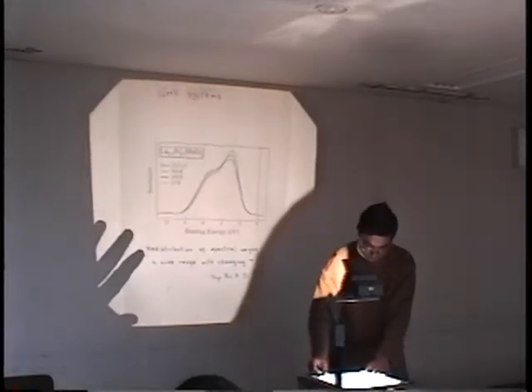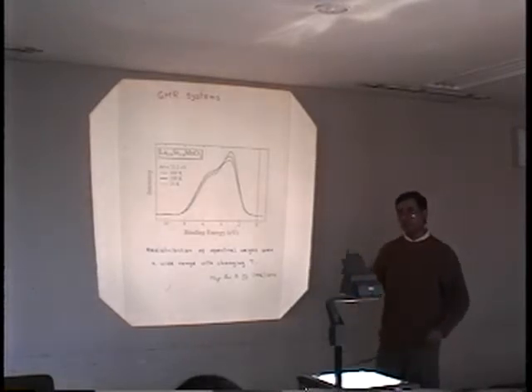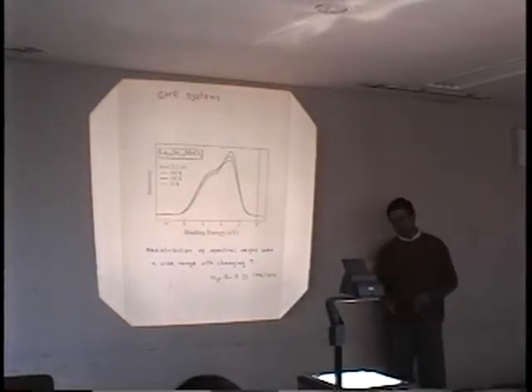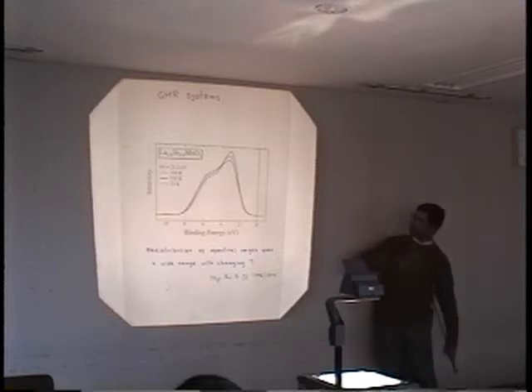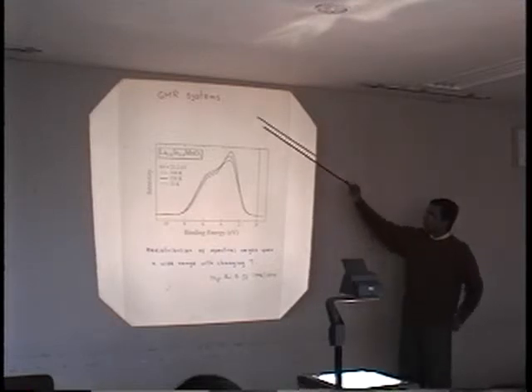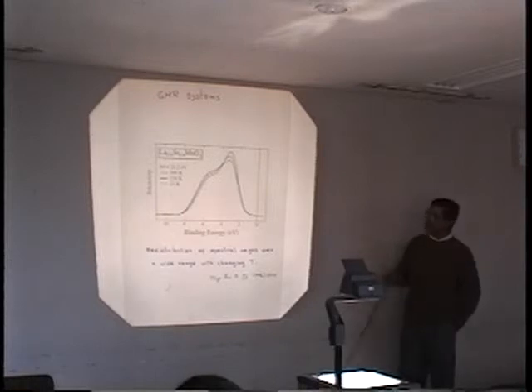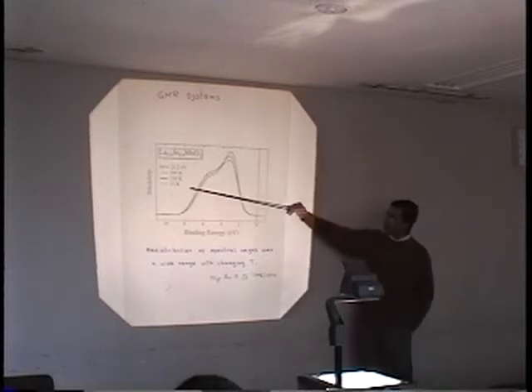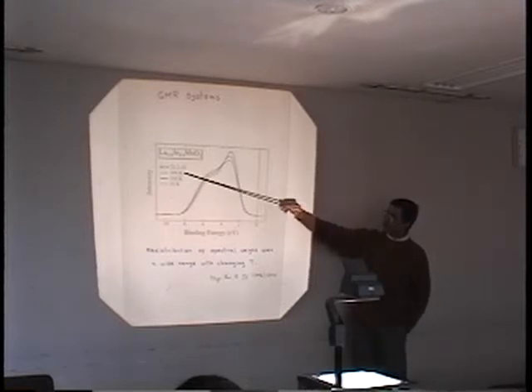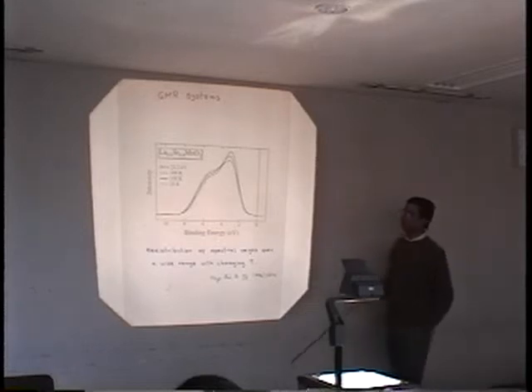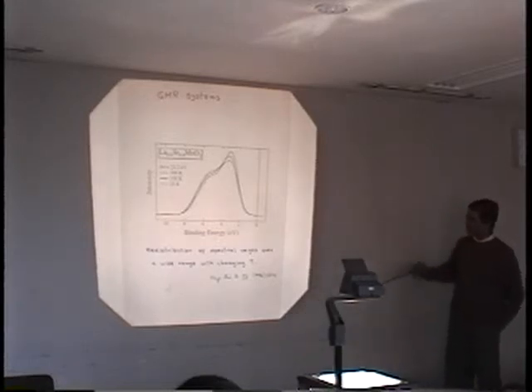Then, this was all in 92. We did this experiment. We published several papers in 93. It took us another 3 years, or 2 years, to do the kind of experiment we wanted to do. In the meantime, giant magnetoresistance was discovered in these materials. We were working on it before that. So we looked at temperature variation of this system with high resolution. We have recorded at 3 different temperatures here, 25 Kelvin, 100 Kelvin, 200 Kelvin. These experiments were done both in Tokyo as well as in Germany, in Berlin.